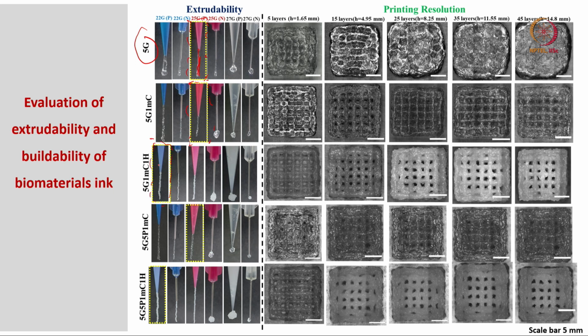When you add the hydroxyapatite, even the 22 G plastic nozzle is good. Now, when you add hydroxyapatite with 5% GelMA, 5% PEGDA, 1% modified carboxymethyl cellulose, and 1% hydroxyapatite, this is good. So, essentially the selection of nozzle size and nozzle type, whether you go for plastic or metal, depends on the extrudability of the specific hydrogel composition, right. So, that is very clear.